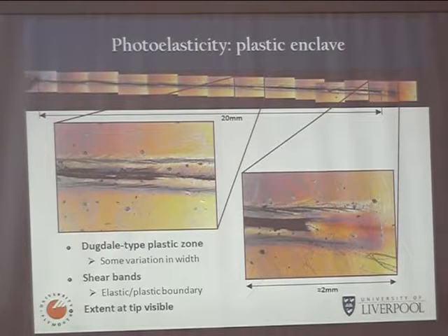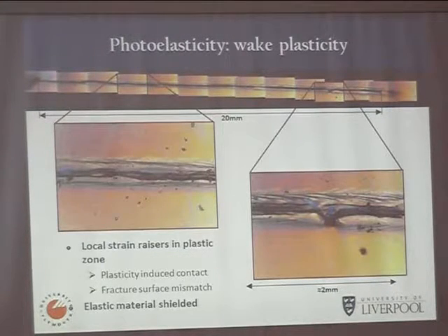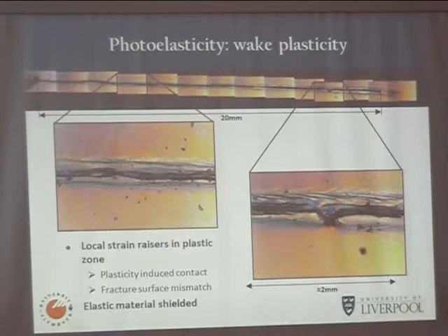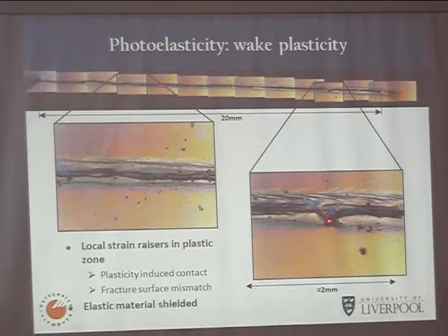Okay. And there are shear stresses, that's what these fringes along the edge of this shear band are showing. So these are the shear stresses that we were talking about a few minutes ago. They're not at the crack flanks, they're at the interface between the elastic and the plastic zones. And if we look at images just a bit further back, for instance there's a little inclusion here in the polycarbonate, you can see how the crack grew down into the inclusion and then out again and carried on. But the elastic plastic zone interface didn't change shape very much in the process.